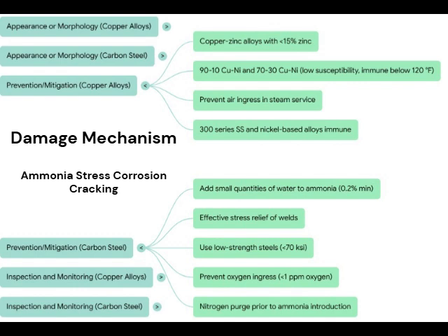And if you just can't stress relieve some massive field-erected tank, what's plan B? Well, material choice still plays a role. Using lower strength steels helps. Steels with a minimum tensile strength not over 70 KSI, they tend to be less susceptible. But the most common and reliable control in the field is actually chemical. It goes back to that magic number. Add water. Ensure you have a minimum of 0.2% water mixed into the anhydrous ammonia. Ah, the inhibitor. Just add 0.2% water.